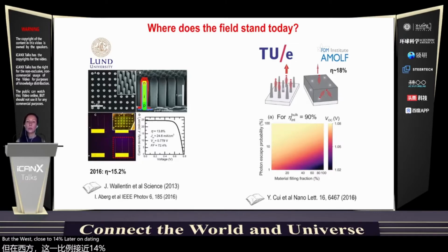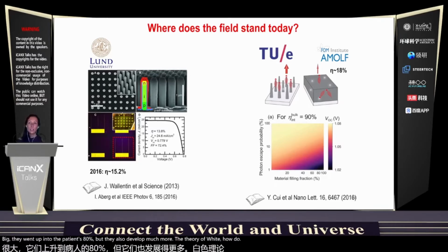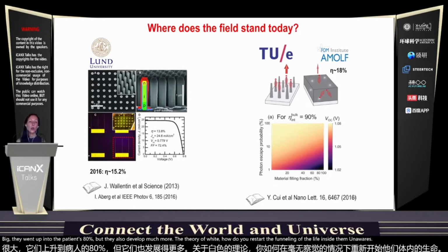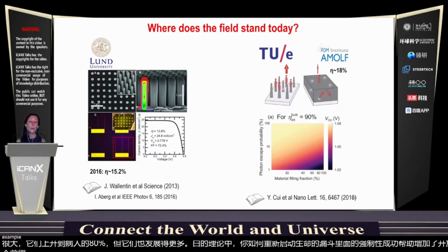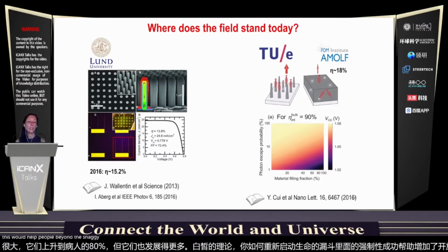And in collaboration of the TU Eindhoven and AMOLF, in fact, they went up to an efficiency of 18%, but they also developed much more the theory of why having this sort of funneling of the light inside the nanowires helps increase the open circuit voltage of the cell. And this, in fact, if you would have a perfect cell, this would help you go beyond the Shockley-Queisser limit in efficiency because of this increase in open circuit voltage.